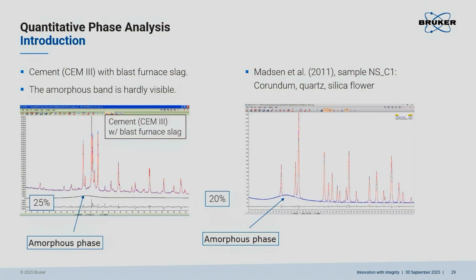Why is that important? Now, on the left side, you see a cement again with some amorphous phase, 25%. Now, this line here, this is the model used for the amorphous content here. So it assists the eye a little bit, but if you would look at this pattern without this intensity distribution here, would you say, hey, this is actually 25% amorphous phase? So amorphous content is overseen a lot, and therefore it is ignored, willingly or unwillingly. But even if you cannot see amorphous content by eye, it can have a substantial abundance in your sample.